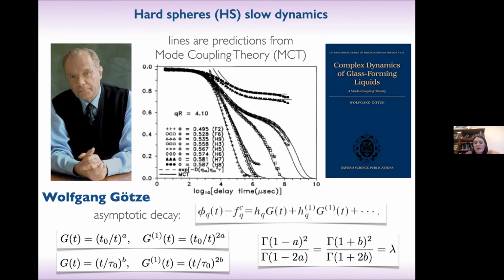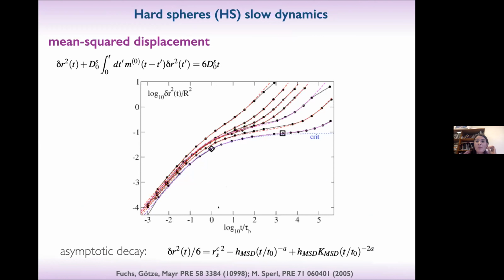These a and b are coefficients that are related to each other by this mathematical equation, and they are defined once and for all. They only depend on the interaction parameters, on the structure factor, and on the number density that you input. Why am I saying that? Because for a standard glassy behavior, you have this two-step decay, and the plateau behavior is described by power laws. The same applies to the mean square displacement. Goetze and co-workers, and also Matthias Sperl later, this is actually taken from a paper by Matthias Sperl, did the same critical expansion for the mean square displacement, which follows a similar power law behavior, and this fits the data of our spheres very well. So you have experiments and theory again.